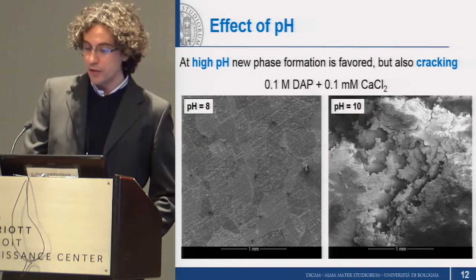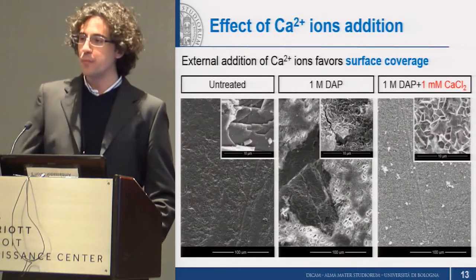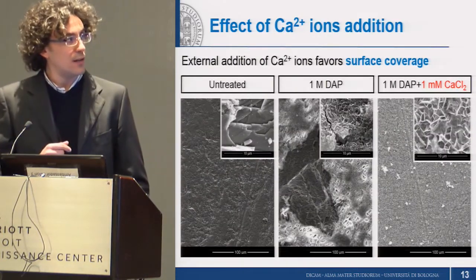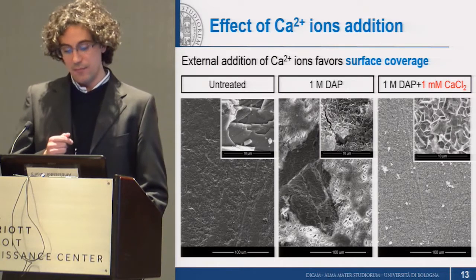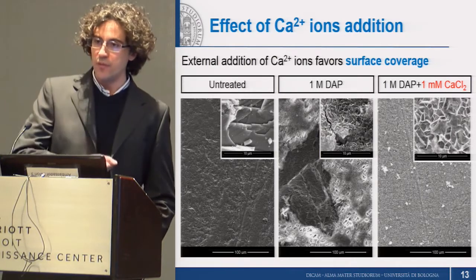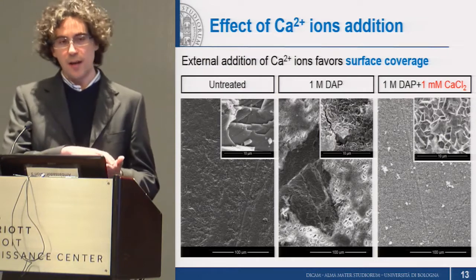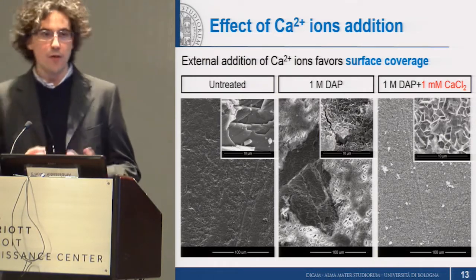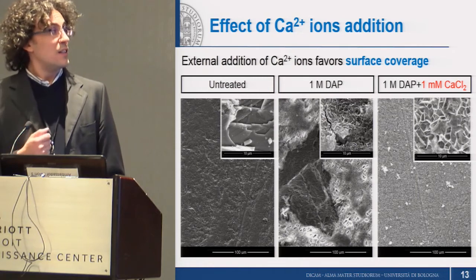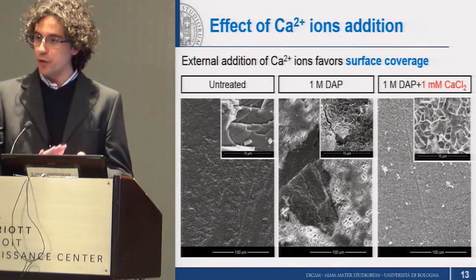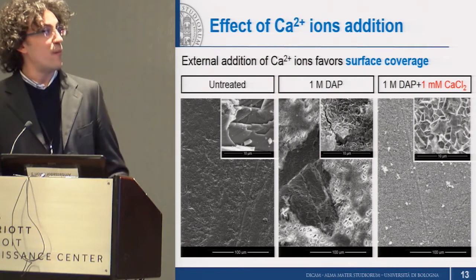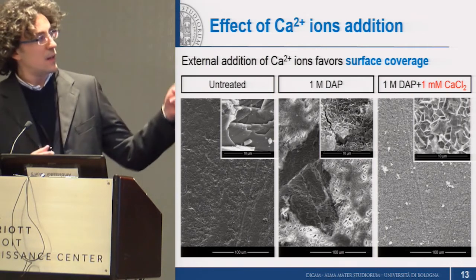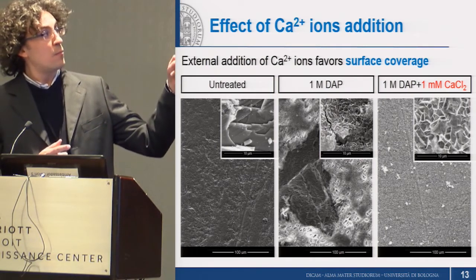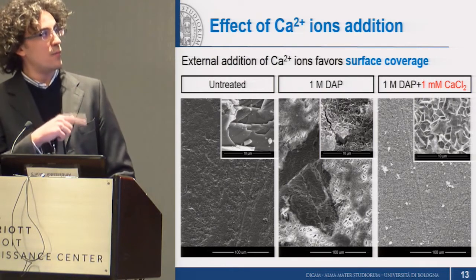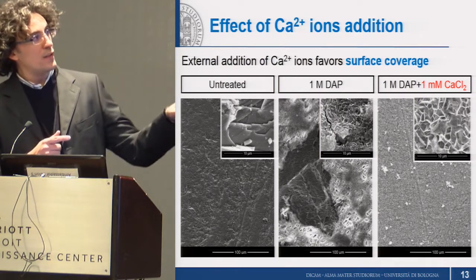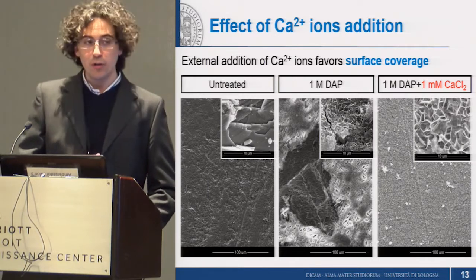Then another important issue was the possible addition of ions, in particular calcium ions. And we found that by providing calcium ions from the exterior, so that in the end they are not only coming from the dissolution of the substrate, but they are already available in the solution, this strongly helps formation of a continuous coating on top of calcite, on top of marble, which is what we wanted. So in this case, you can see the difference by using a 1 molar DAP, which is diammonium hydrogen phosphate, with and without addition of 1 millimolar of calcium chloride.